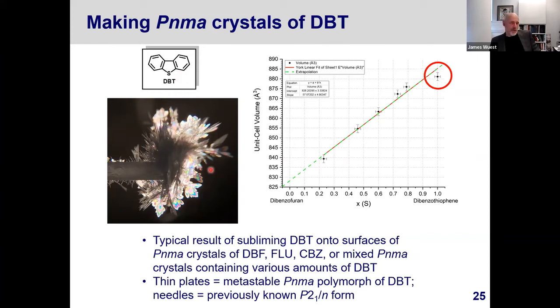And if you look at this carefully, you can see something. If you remember the initial pictures I showed you of the crystals that are characteristic of the thiophene versus crystals that are characteristic of the furan, you can see a cluster of needles here. Those are the regular form of the thiophene, but all these flat plates out here, these are the new form of the thiophene that have been induced by crystallizing on surfaces of the PNMA structure of whatever the seed is.